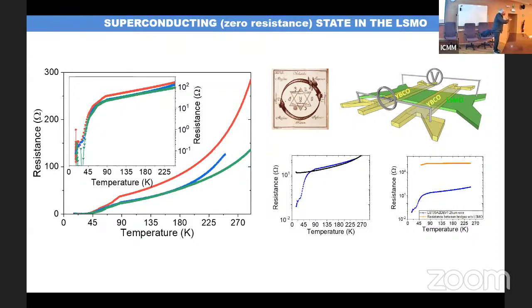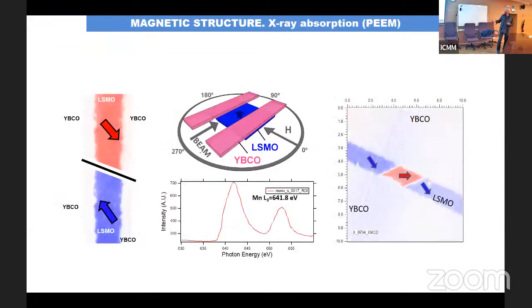And we even did devices without manganite wire, to look for shorts, and there was not. There was not. And so we were convinced that we had made the manganite superconducting. So we looked for a possible explanation, that maybe the manganite has degraded, it is non-magnetic. We went to the synchrotron and we did photoelectron microscopy with X-ray magnetic dichroism contrast. And we made sure that the manganite remained magnetic with this biaxial anisotropy in the plane of the wires.